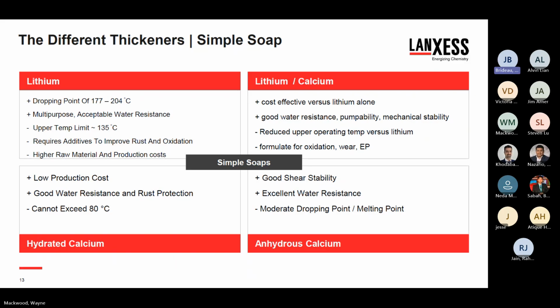The blending of lithium and calcium is one thing people are using to get around some of the issues faced with the cost of lithium metal and lithium hydroxide from the battery market. There are companies that have had lithium calcium on the market, but others are getting into that. Basically, it's just a co-reaction of lithium hydroxide and calcium hydroxide with 12-hydroxystearic acid. You just replace some of the lithium hydroxide with calcium hydroxide. The temperature performance drops a little bit, but overall, they're not a bad product for the applications they're used in.